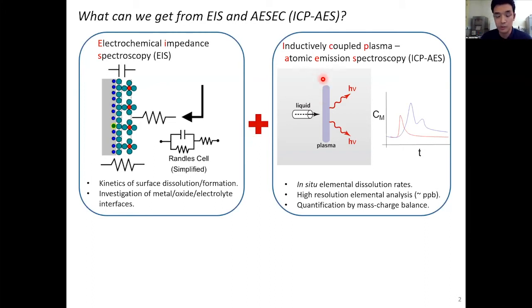And the AESEC technique, which has been presented several times during this afternoon, allows us to measure the elemental dissolution rates as a function of time. So in this case it is concentration as a function of time, and this generally shows really high resolution. Atomic emission spectroscopy is normally at the ppb level, and mass spectroscopy is even lower than the ppb level. And it has been demonstrated that quantification by this technique is totally reliable, so that we can measure quantitatively how many cations are dissolved in the solution.